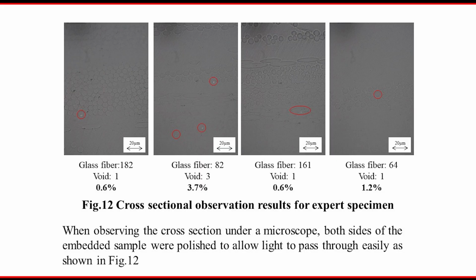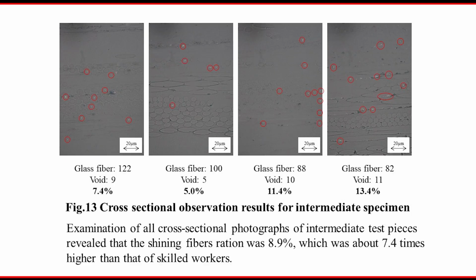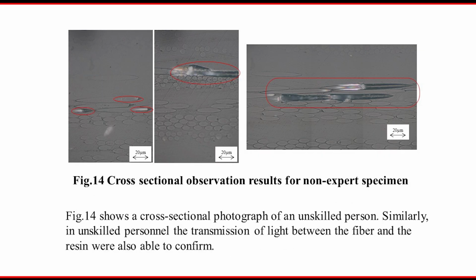So that percentage is the void ratio. Then this is the intermediate specimen. On the left side, we can see 122 glass fiber filaments, and we can see 9 voids. So the void content is 7.4%. And then 100, 5, 88, 10, 82, 11, and so on. So the void content is larger than the expert. And this is a cross-sectional photograph of the unskilled person. Similarly, in the unskilled person, transmission of light between the fiber and resin was also confirmed. We can see some voids, and very large voids can also be seen.